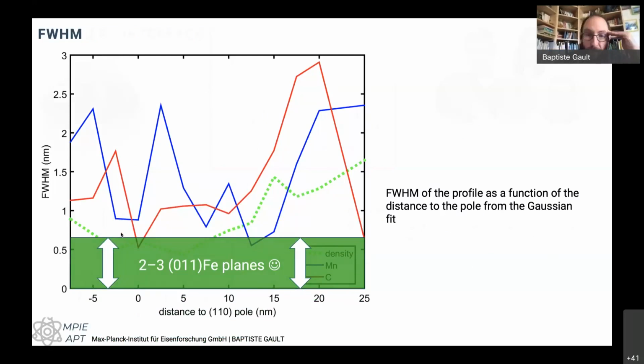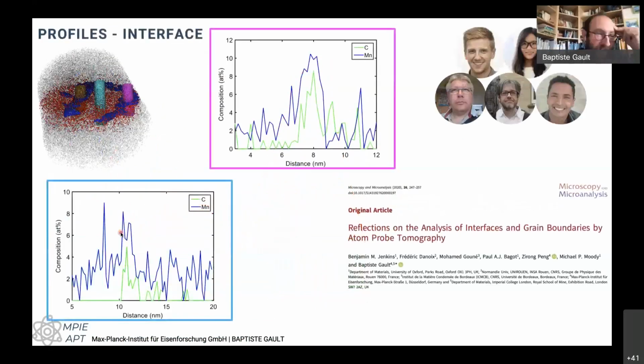There are fluctuations along the way, and you can see that, and it's partly because there's a slight mismatch in the orientation relationship between the two grains, which means that every maybe 20 nanometers or something, there's a need for a dislocation to accommodate the change in orientation. And these dislocations actually suck up a lot of the manganese and carbon. So it made my analysis a bit harder than it should have. But we can actually go down to imaging how much segregation there is right at this interface.